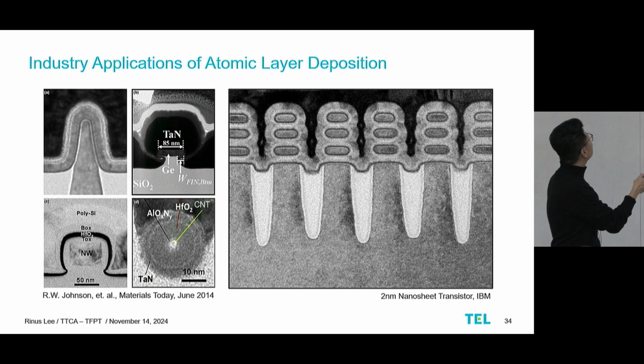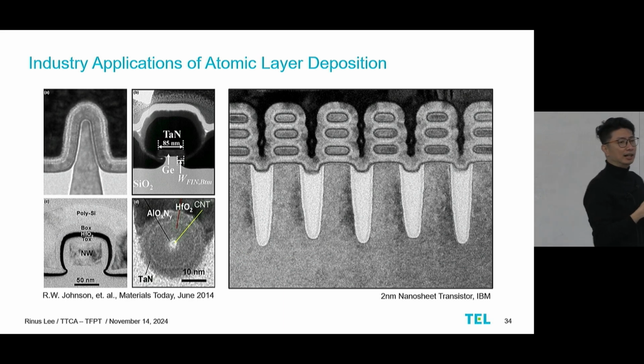So the next few are just examples. For example, this is a nanowire sheet. So you could imagine if we use a directional deposition, the metal or the particles will come down this way, which means you have deposition on this side, but not on this side itself. But by using atomic layer deposition, because it's reacting with the surface, so this is the entire surface. As long as the chemical comes in, it will react with the surface, therefore forming a film itself. So you could see in this example, it's forming an aluminum oxynitride and a hafnium oxide itself by self-saturating. So this definitely gives us a lot of control over these advanced structures.